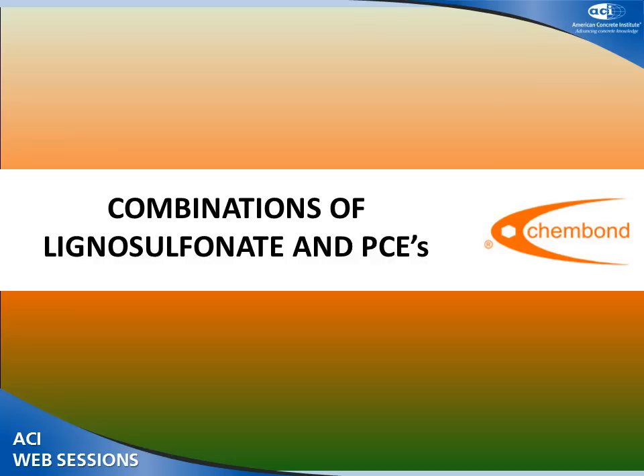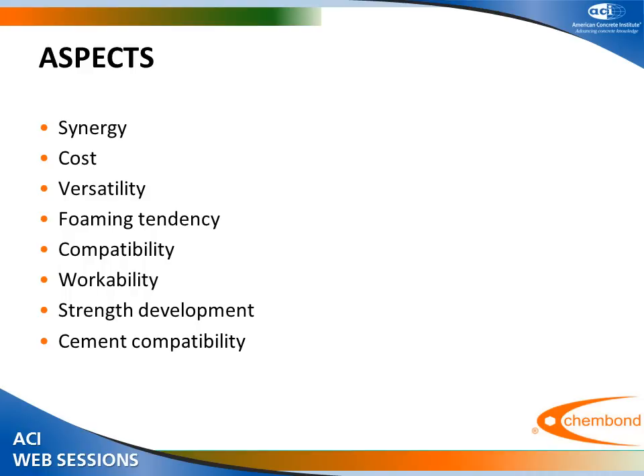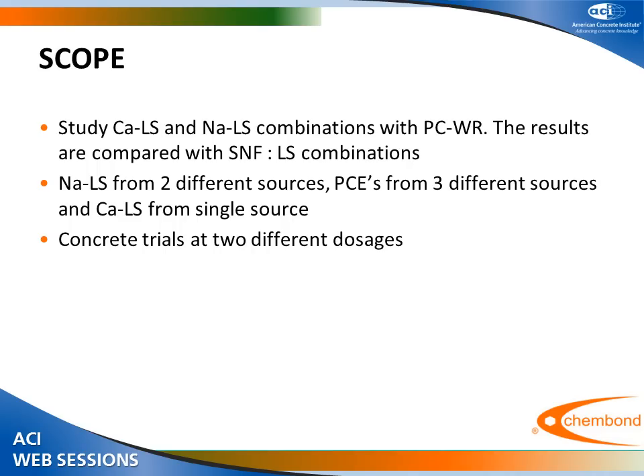So this is now for the combinations. Main aspects of this study were involved to check the synergies, costs, versatility, foaming tendency, compatibility, workability, strength development, and cement compatibility. We have used calcium lignosulfonate and sodium lignosulfonate combinations with water-reducing type polycarboxylate. The results are compared with SNF and lignosulfonate combinations. We have used sodium lignosulfonates from two different sources, polycarboxylates from three different sources, and calcium lignosulfonate from single source. And we have conducted concrete studies at two different dosages.